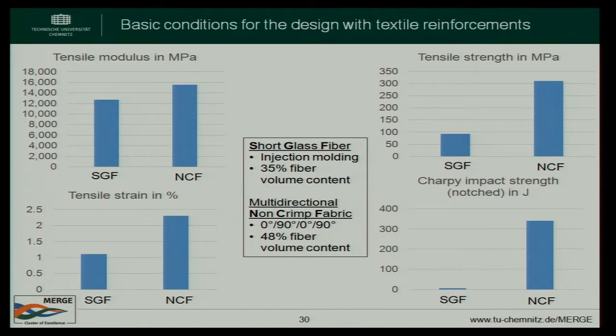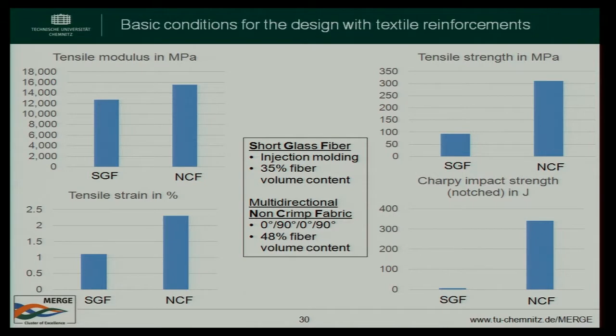Because with short fibers, if you have some crash, the fibers will be pulled out of the matrix. It depends also on your fiber matrix adhesion. But the longer the fibers, the more energy absorption you have in the friction between fiber pull out and matrix. You reach really only 1/20 of the properties of endless fibers with short fibers. Okay? So it depends on the boundary conditions you get from your customer, which properties you want to increase in the part. If you are focusing on stiffness, then sometimes it makes sense to use only short fibers because this is an easier process in making the part. If you are looking at impact, at strength, then it makes sense to use endless fibers, but related to stiffness, short fibers may already be sufficient.